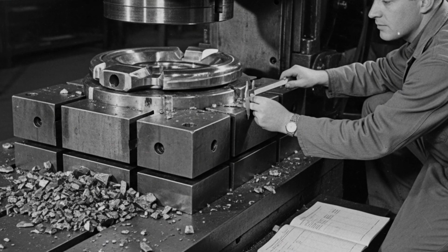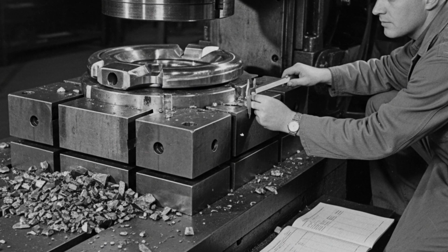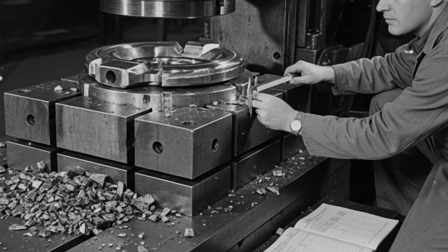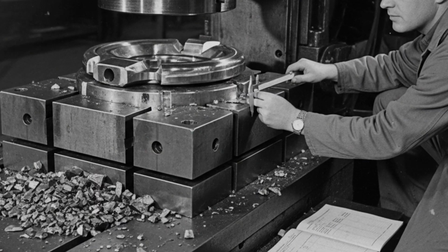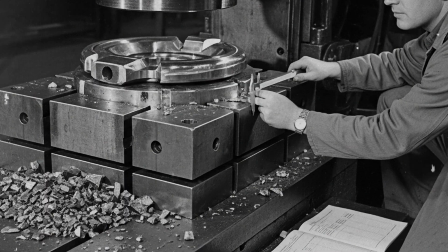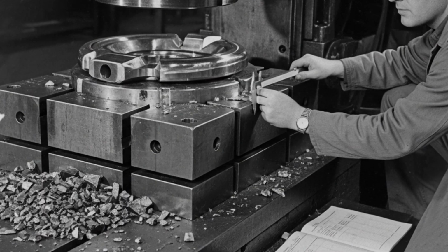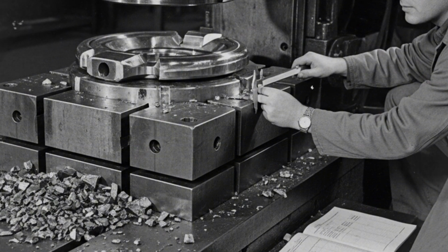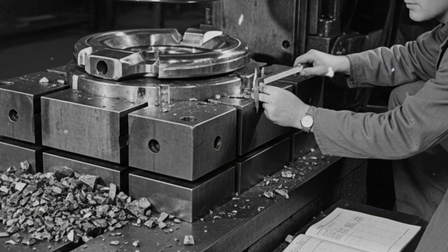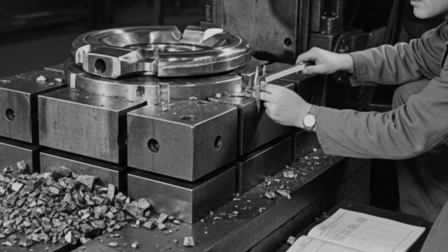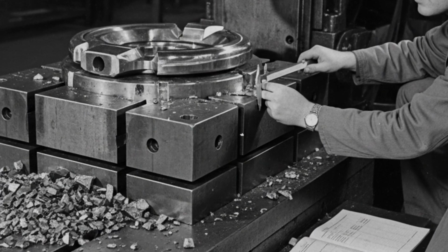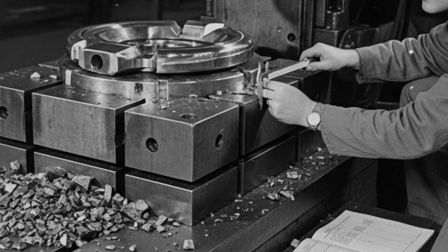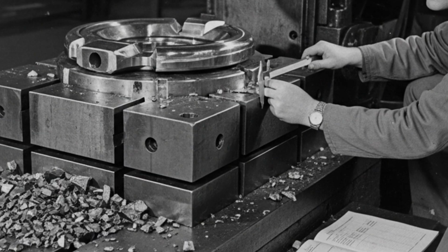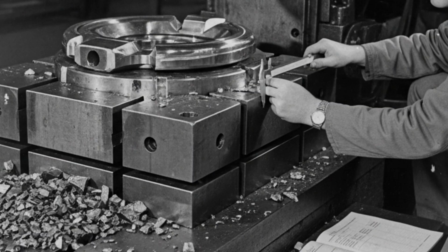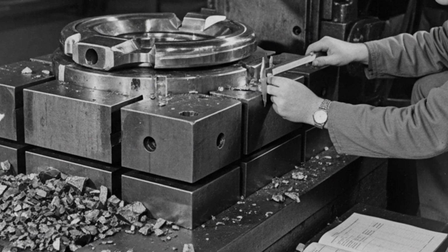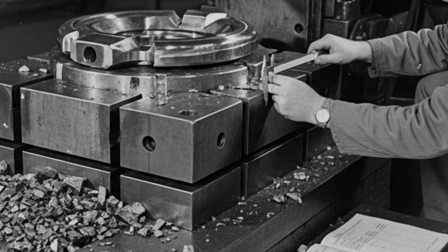If the billet is positioned with even slight angular misalignment relative to the die cavity, the initial contact geometry creates asymmetric lateral loads that the die clamping system must absorb. These asymmetric loads, if they exceeded the clamping force, produced a lateral displacement of the lower die, a phenomenon called die shift, that was detectable only by dimensional inspection of the finished forging, by which point the press had already completed the stroke.